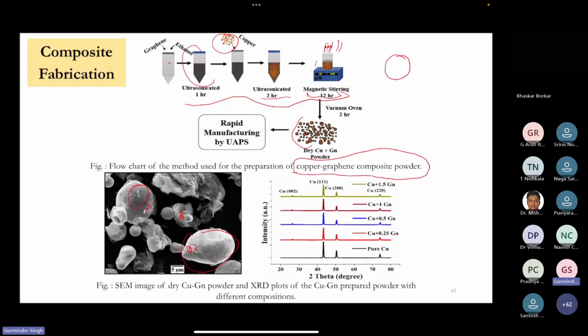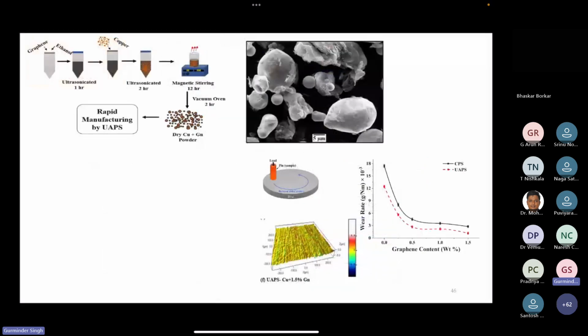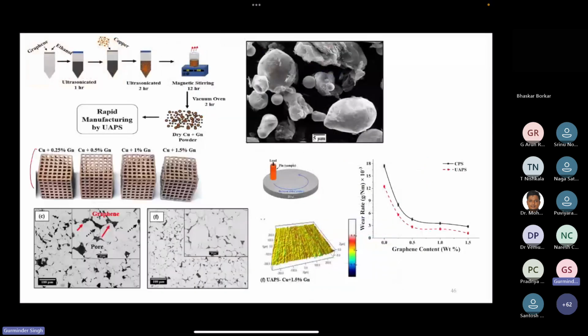We dried it in a vacuum oven for 2 hours, and then we use this powder as the raw material for our 3D printing process. After going through this process, we were able to make composites of graphene up to 1.5 percent. Now there is a glitch here.